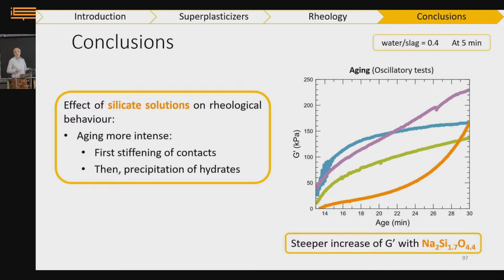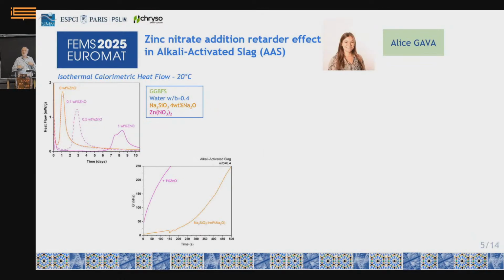So, okay, he has an explanation, you believe me or not, but then so what? So what is that now we understand that what we have to control is this phenomenon associated with a high initial silicate concentration. So if we add a retarder, for instance, zinc nitrate, this zinc nitrate has to mobilize the silica initially to prevent this sol-gel phase separation. And in our opinion, this is why zinc nitrate, here expressed as zinc oxide content, is such a good retarder.